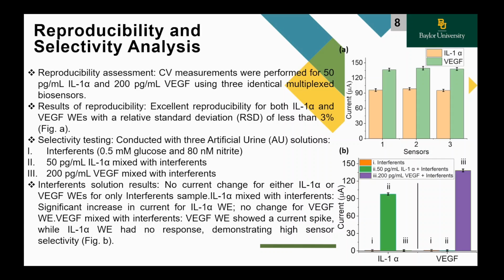The selectivity testing was conducted with 3 artificial urine solutions. First one, just interferent. We used the 0.5 millimoles glucose and 80 nanomoles nitrite. Second one is the 50 picogram per milliliter interleukin-1 alpha mixed with interferent. Third one is the 200 picogram per milliliter VEGF mixed with interferent.